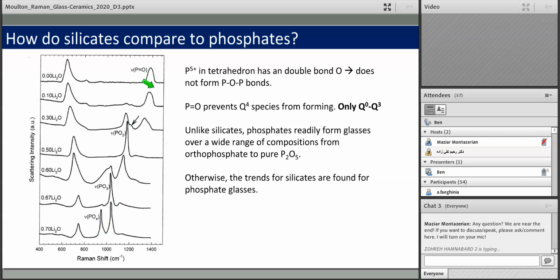At the top is pure phosphate glass with 0% lithium. As we increase the lithium content all the way to the super phosphate here with more lithium than the orthophosphate composition, we see a smooth shift to lower frequencies related to the Qn phosphate species, with the only difference that there's an extra band here at the highest frequencies related to this double bond.